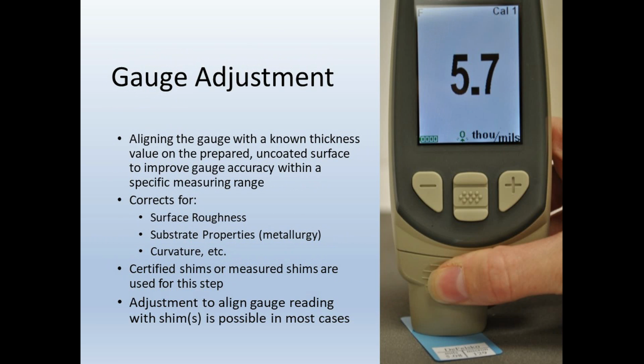But remember, we're not putting the paint or the lining system over smooth steel. We're putting it over a roughened surface. So we have to compensate for that. And so we do that by using measured shims or certified shims and placing those on the blast clean steel. Adjust our gauge to match that shim. That way we're only recognizing the amount of coating that's sitting on top of the profile.